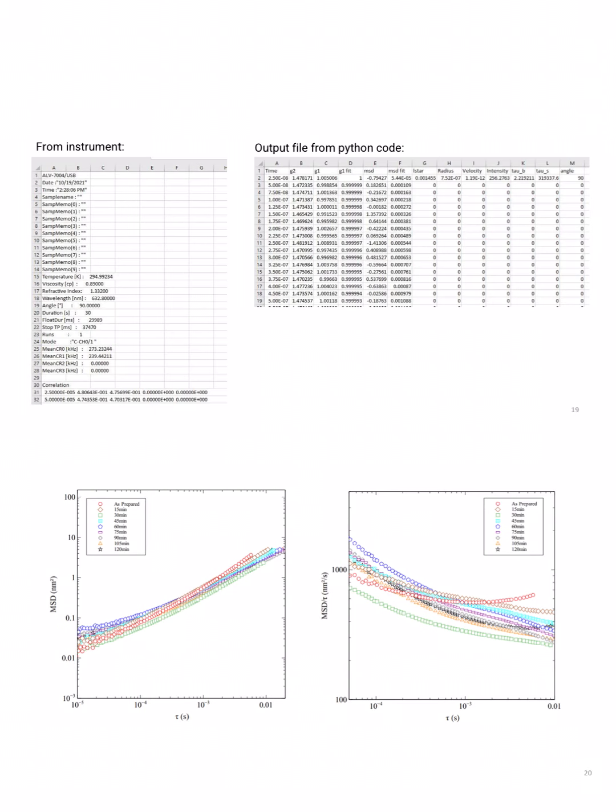The bottom panel shows an example of an experiment I ran recently. On the left is an MSD plot. The curves look fairly linear, although when I scale MSD by time on the right, you see the slope is negative and the sample is actually showing subdiffusive behavior. Therefore, the radius cannot be accurately reported using the current code.